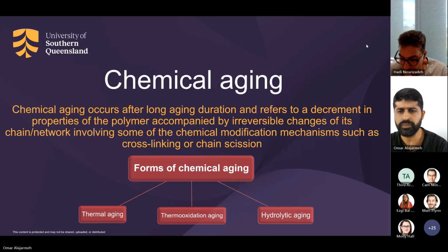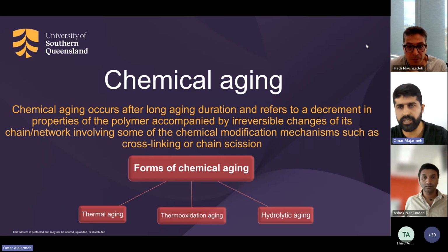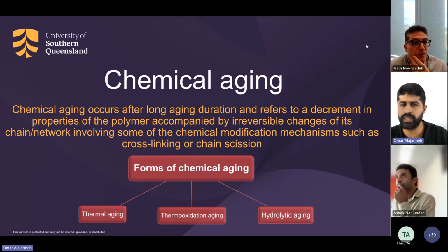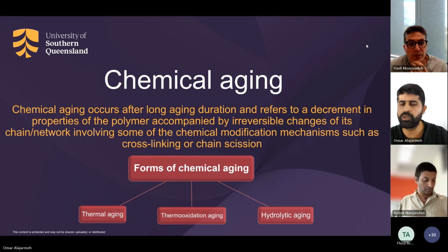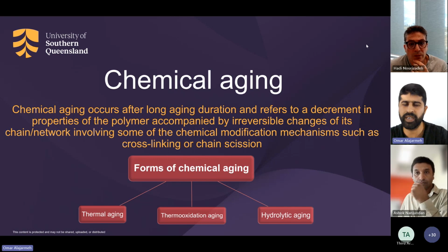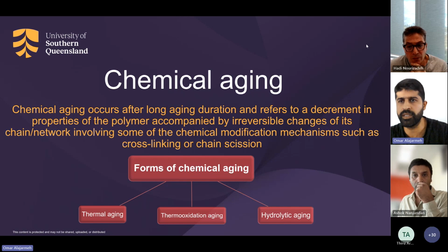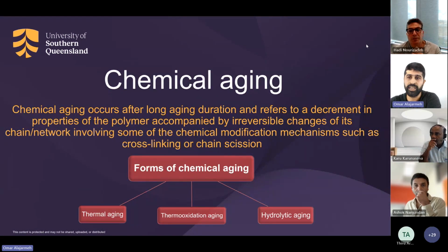For thermal aging, what we mean is molecular deterioration coming from overheating, meaning a temperature close to Tg or over that. What are the features that you can see from thermal aging? One is a reduction in ductility and seeing some brittleness in the polymer. The second is a color change, so you will start to see a yellowish side of the polymer. Also micro cracking and debonding between the fibers and the polymer, and a reduction in physical properties, like an increase in moisture absorption and all of these things.